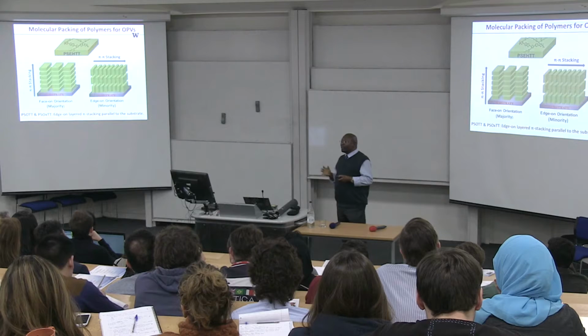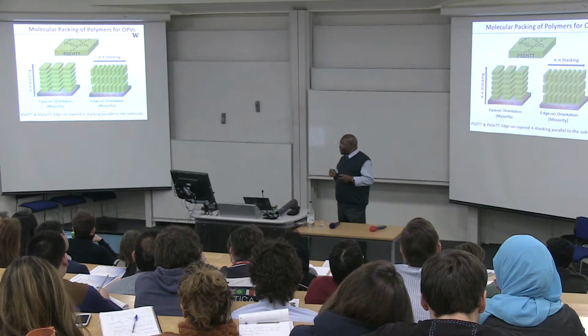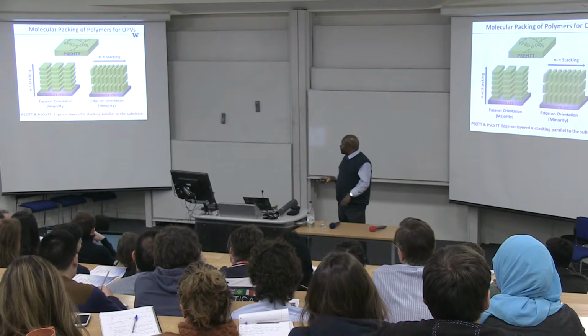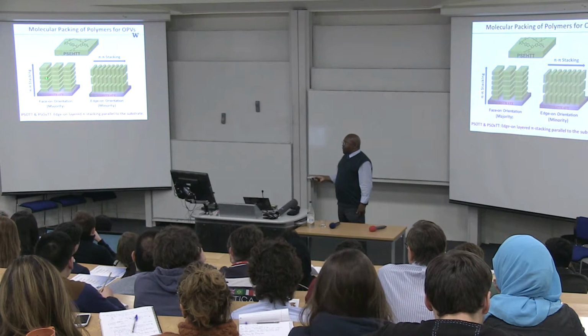This is actually very important for solar cell applications, because in fact, this is what we would prefer if we were to know how to do it. We don't really know how to design a polymer that will preferentially pi stack that way. This we discover by having a large library, and by experimentation, we found that this polymer packs that way, but clearly suggesting that perhaps by doing side chain engineering, by keeping the backbone, and you do side chain engineering, that